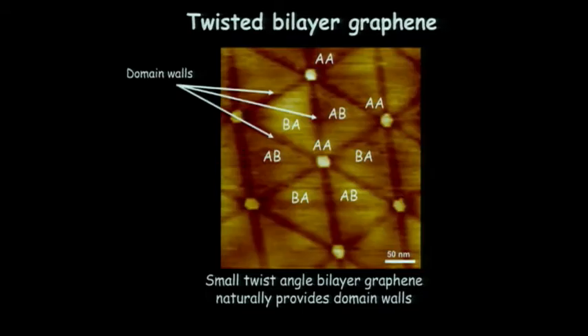So in our case, we have these long wavelength Moiré patterns, and so we have well-defined AB and BA regions. And then between them, there are these dark lines here. These are domain walls. And they are connecting the AA stacked regions, which show up as a bright spot in our STM measurements. And so we have AB, BA alternating around with the AA in the center. And so we naturally get these domain walls in our sample. And so the idea then is to go and do spectroscopy and look at how the spectroscopy varies at the different locations in this unit cell.